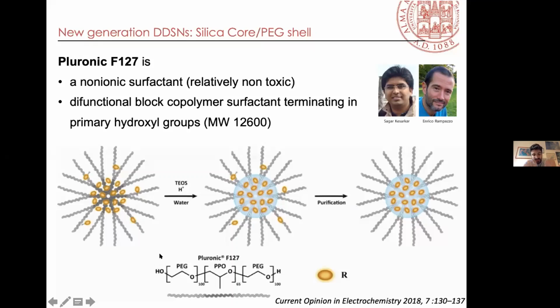The advantage of the micelles, of course, it's obvious, but micelles have a hydrophilic shell and hydrophobic core. Okay, nice. So you can use this hydrophobic core to embed dye not soluble in water, for example, diphenylanthracene or some molecules that are fully not soluble in water. And after that, you can grow the silica core within the center of the micelles, and you can have very nice and stable nanoparticles with the hydrophobic dye in the middle, and this allows you to use hydrophobic dye as ECL emitter in water. That is one of the very important points.